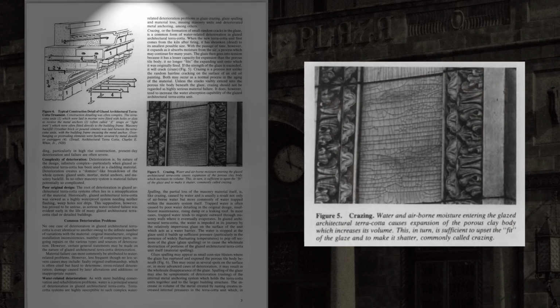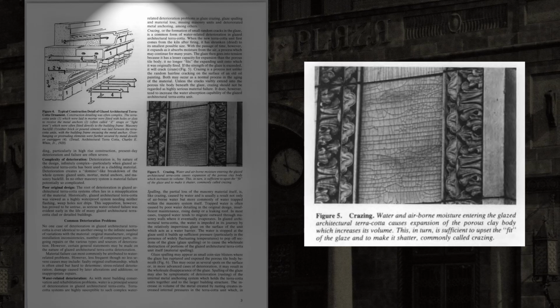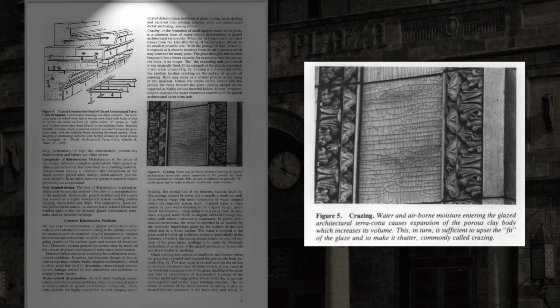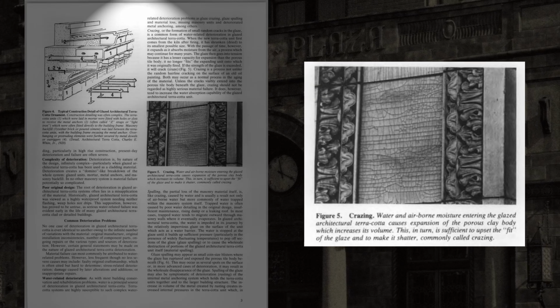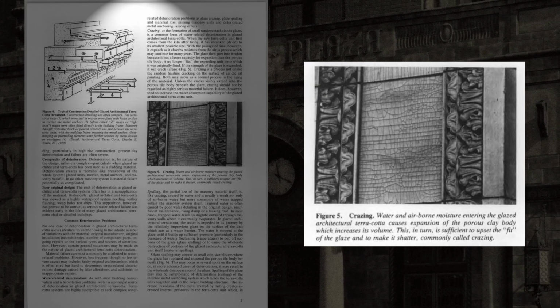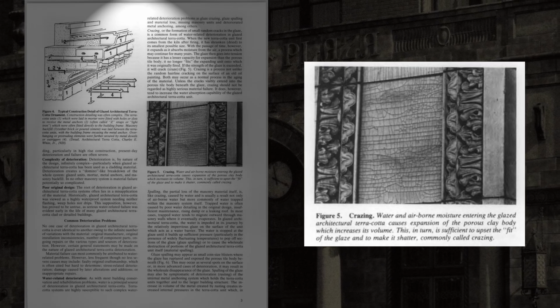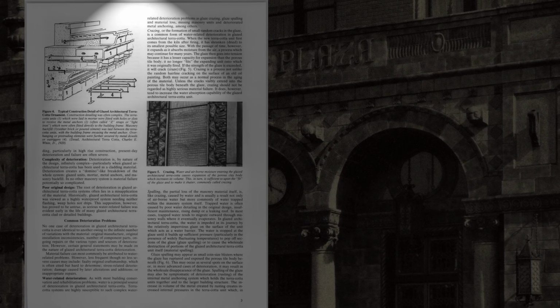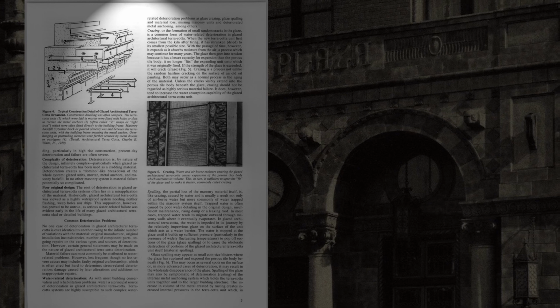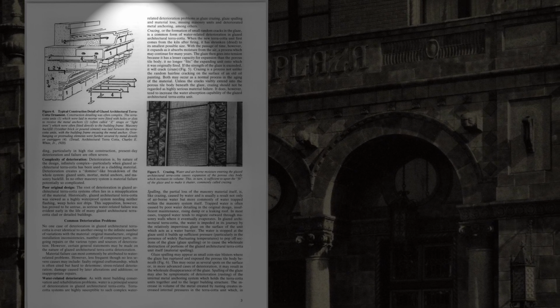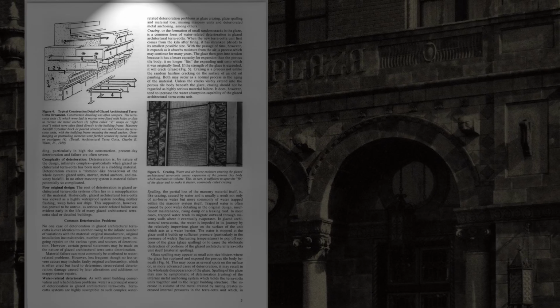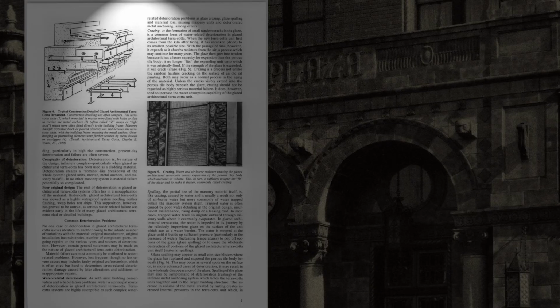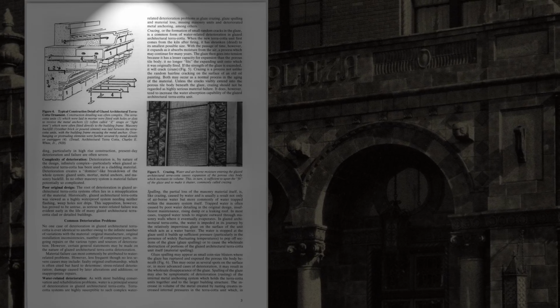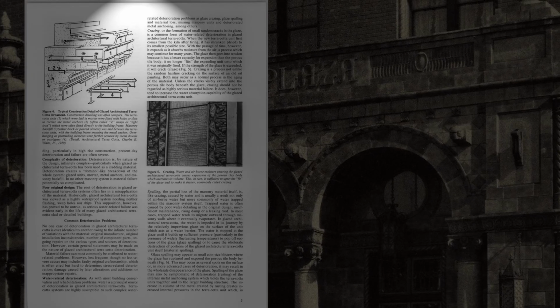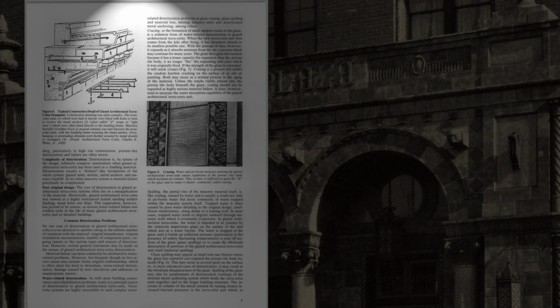Figure 5. Crazing. Water and airborne moisture entering the glazed architectural terracotta causes expansion of the porous clay body, which increases its volume. This, in turn, is sufficient to upset the fit of the glaze and to make it shatter, commonly called crazing. Crazing is a process not unlike the random hairline cracking on the surface of an old oil painting. Both may occur as a normal process in the aging of the material, unless the cracks visibly extend onto the porous tile body beneath the glaze. Crazing should not be regarded as highly serious material failure. It does, however, tend to increase the water absorption capability of the glazed architectural terracotta unit.